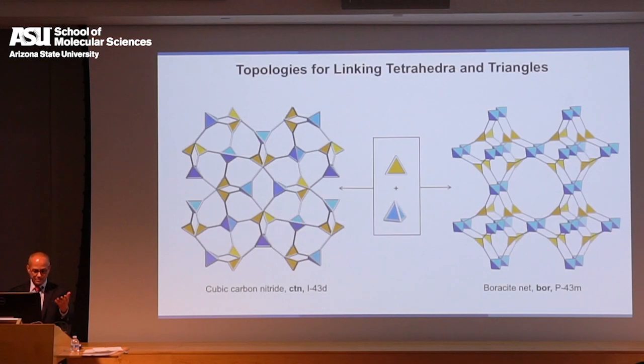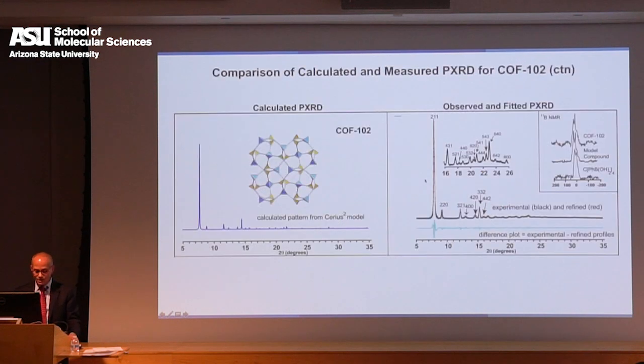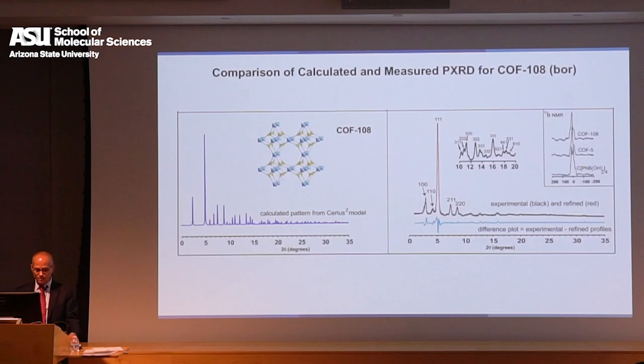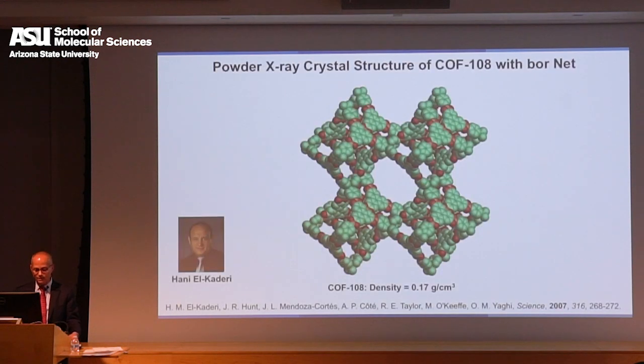These are the nets that Mike had predicted for joining triangles with tetrahedra. These are the two most symmetric possibilities, and both of them we made by matching the simulated X-ray powder diffraction to the experimental powder diffraction. That gave us the initial model to refine the structure. This turns out to be one of the least dense materials known to date. It's entirely composed of boron, oxygen, and carbon linked by covalent bonds.